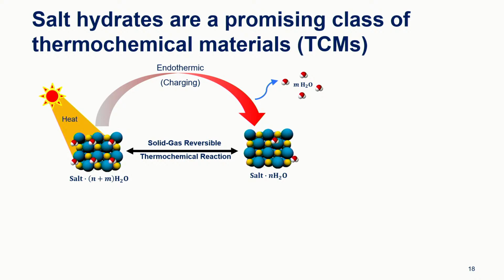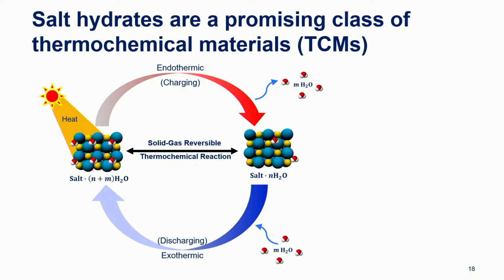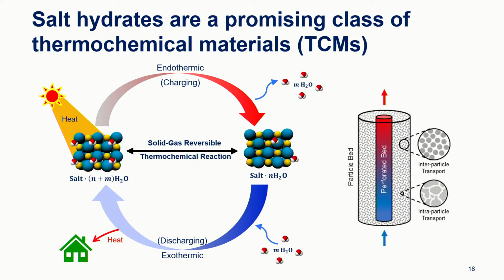And then when we want to release that energy, we just run the reverse reaction where we introduce water molecules, in the form of relative humidity, and that creates an exothermic chemical reaction where the salt is hydrating again, and that process allows you to discharge the heat that is stored. And we would discharge this heat for a building application. So we're looking at designing a packed bed reactor with these thermochemical salt hydrates in order to charge and discharge energy as heat. So this is thermal energy storage at temperatures under 100 degrees Celsius for buildings.